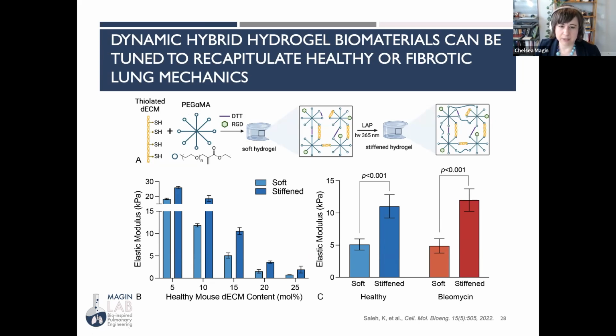of chronic disease. When we combine these two materials using a Michael addition reaction, so we just increase the pH a tiny bit to be basic, we can create a soft hydrogel. This hydrogel can mimic healthy lung tissue. And then we can stiffen the hydrogel by exposing the whole system to a photoinitiator and 365 nanometer light. This initial reaction is done off stoichiometry.